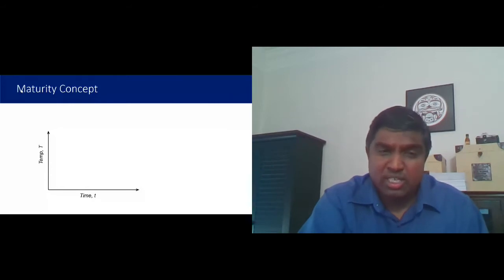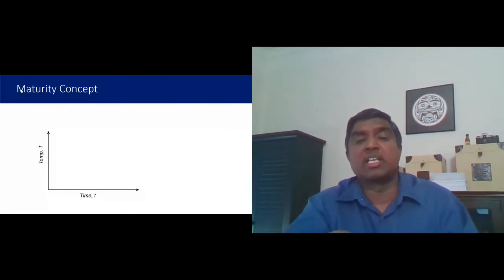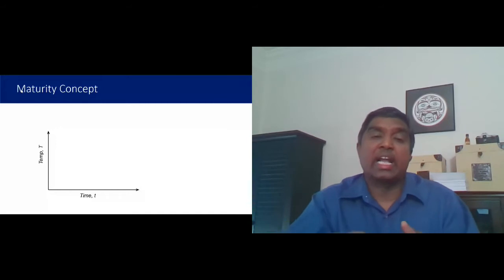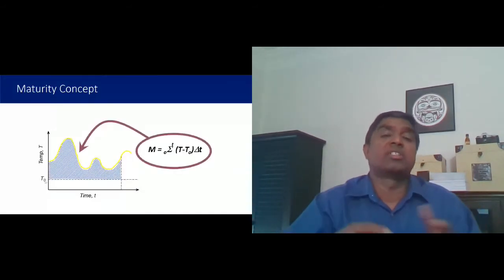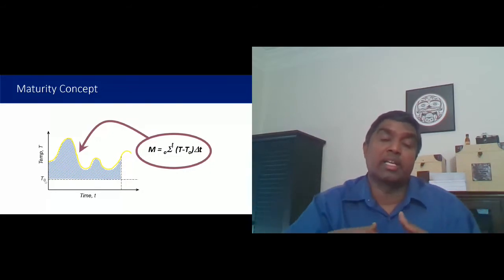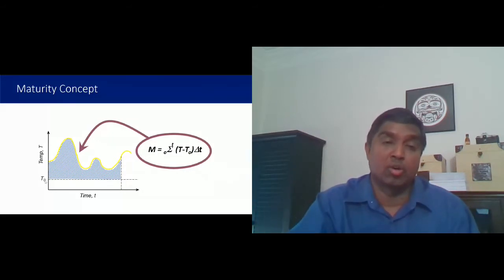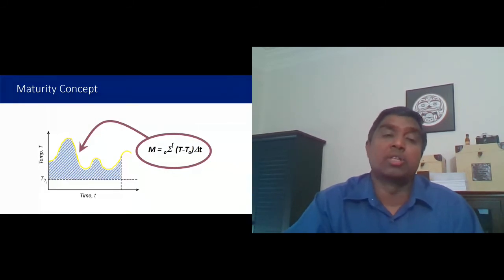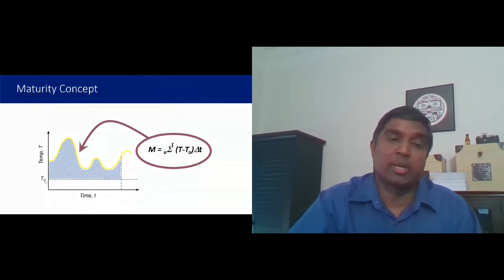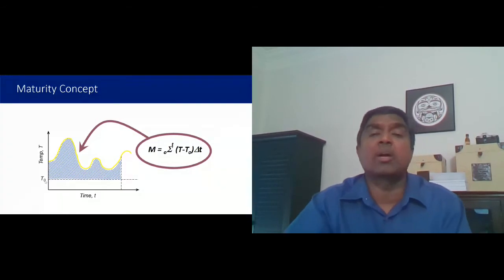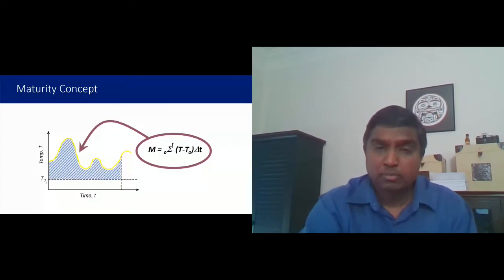Now the term you see here at the bottom, which says T0, is something called the datum temperature. It's a temperature below which the assumption is that there's no hydration taking place or there's no strength gain taking place. So we only measure temperature above this datum temperature, which is represented by T0 here. We'll talk about that a little bit later on.